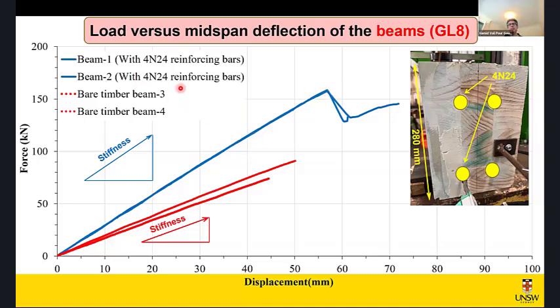You see, interesting in this particular case, it seems it's even the same test, but in fact we did 2 tests and with minimal variability in the results, right? And the slope of these lines, again, I would like to draw to your attention to, it's the stiffness or a measure of stiffness. Now, in this case, up to 89% improvement in the peak load or strength and 72% improvement in the stiffness.